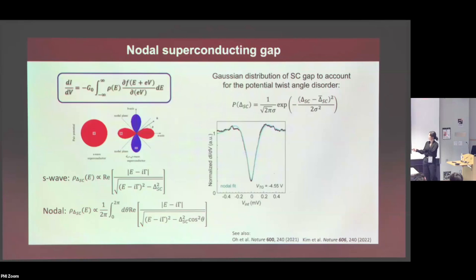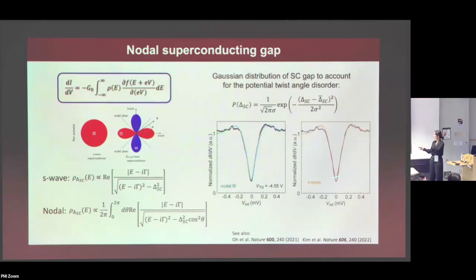And we try to fit that using the nodal fit, and it fits pretty well. You can also try to fit it with the S-wave fit, but it's not that good. I just want to make sure that some of you might be wondering, did you just pick the good looking fits for the nodal fit? I want to assure you that we explored the entire phase space that's possible with all these different parameters, and this is the best fit that we can obtain for the S-wave. So the nodal fit fits better, but some people might say, this is still just fitting, we can fit whatever, so maybe not a conclusive statement.